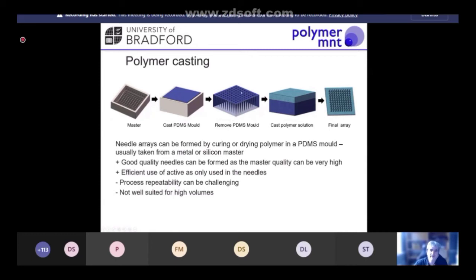Now, they won't be replicated with absolutely perfect accuracy, but it's usually good enough to then cast a polymer solution into that with your active pharmaceutical if you're using a dissolvable system. And then you can let that cure in place and remove it from the PDMS mold, which has very low friction and can deform, so the needle array can be released quite easily, to leave your final microneedle array. So this is a really popular and really common system for making these arrays in the research area.